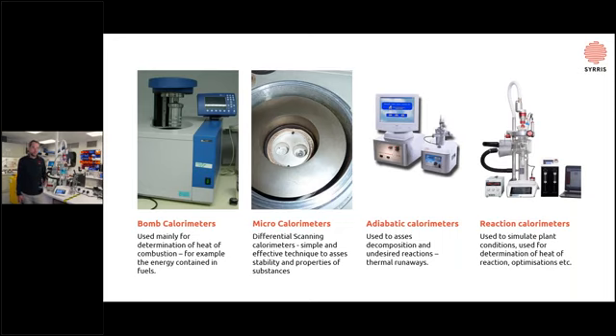So the first one, the bomb calorimeters, are still basically using a similar principle as Lavoisier used in his calorimeter in 1782. They are used mainly for determination of heat of combustion. So we would load the bomb, which is usually a stainless steel vessel, able to withstand high pressures and high temperatures. And we would ignite the sample inside. It would heat up the vessel, which in turn would heat up the water, measuring the difference in temperature, knowing all the parameters on heat capacities. We can actually quantify the energy of the combustion, usually used, for example, for the energy density of coal in power plants. But that kind of calorimeter isn't usually used in process development.